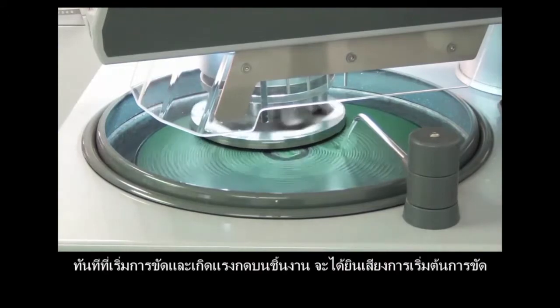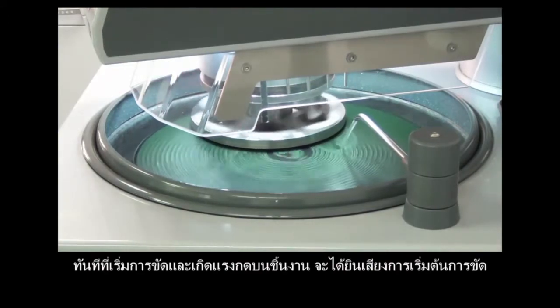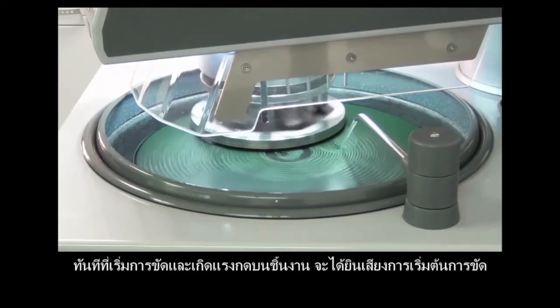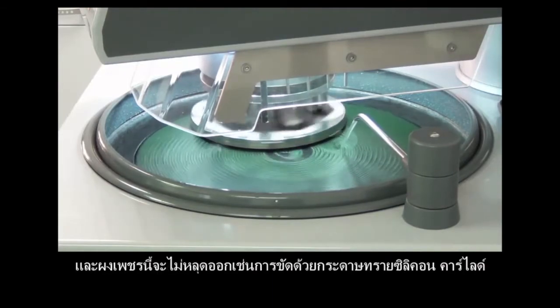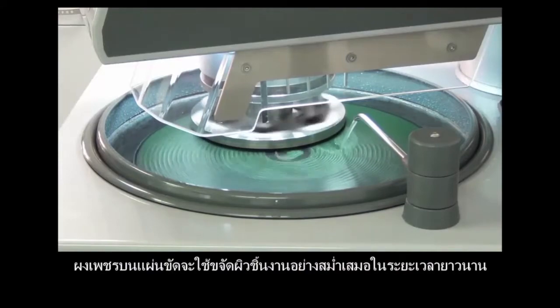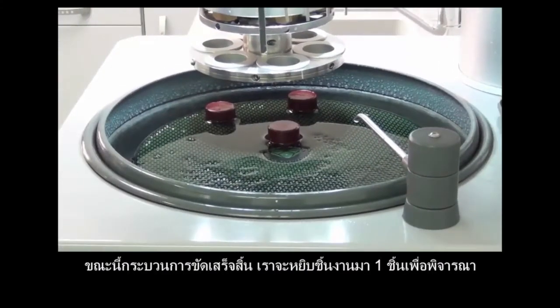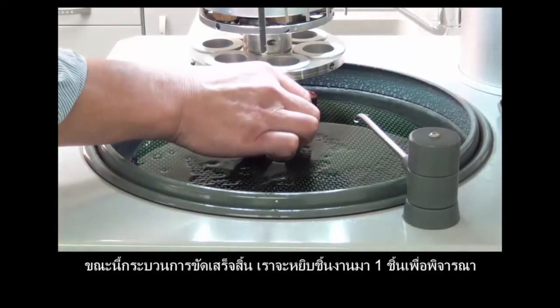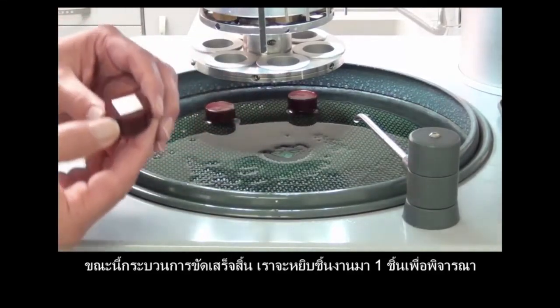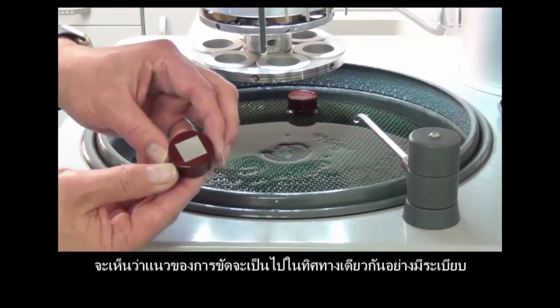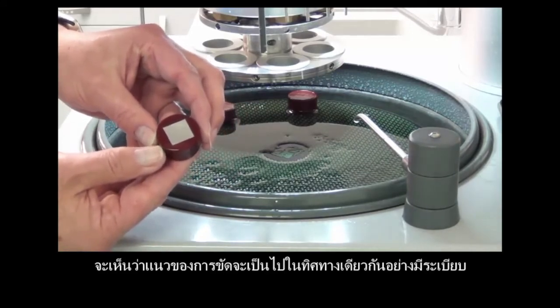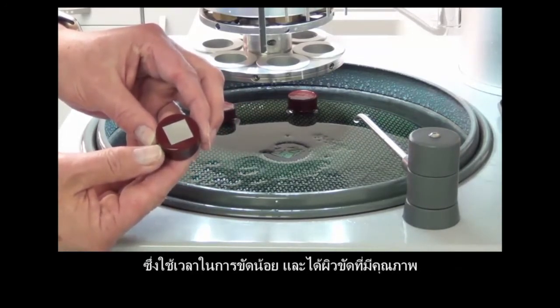You can hear as soon as the force is applied that the grinding starts taking place immediately, and these diamonds, they do not wear like silicon carbide paper. They will have a constant removal over a very, very long time. Now the grinding process has stopped, and we take out one of the samples to have a look, and you can see a uniform grinding pattern over the entire surface. So very short time and perfect grinding result.